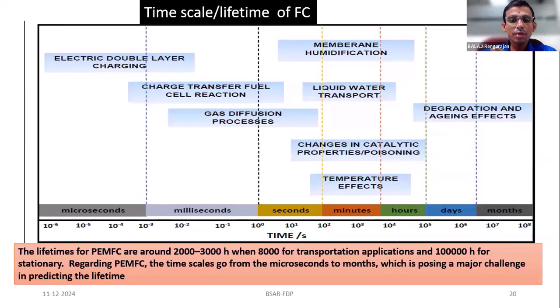And as I said, apart from the power production, water is also a byproduct in the fuel cell. So you need to handle the water effectively. Otherwise, if you do not effectively evacuate the water from the system, it will create flooding, which will slowly degrade the fuel cell performance. All these phenomena happen from microseconds to milliseconds and seconds, and even in terms of days and months. So if you want to ascertain the durability of the PEMFC, multiple parameters and multiple component functions have to be addressed. Only then can you arrive at conclusions about the durability of the PEMFC stack.